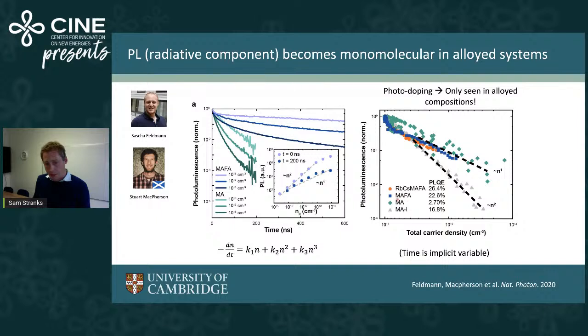But when we start adding other components, so either we add to methyl ammonium a bit of bromide, or we add formamidinium, or we add even other cations as well, rubidium in this case, what we see is the kinetic becomes quasi-first order across most of the range. So as soon as we start alloying these systems, we start to see this photodoping. And I'll go through that a bit more as we zoom in on the microscale.